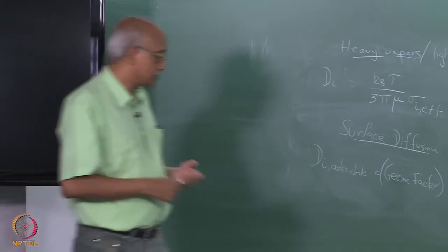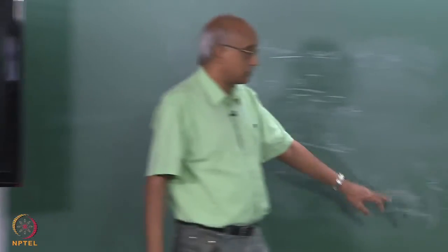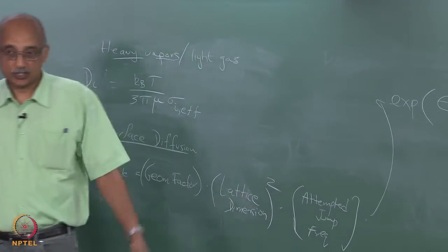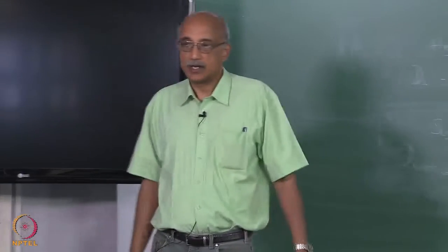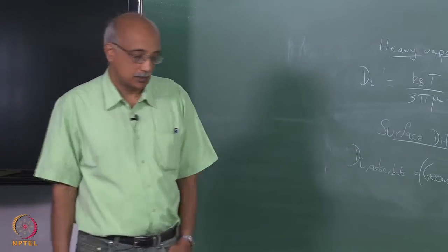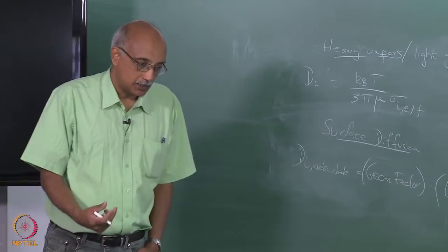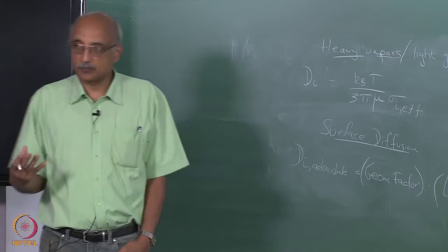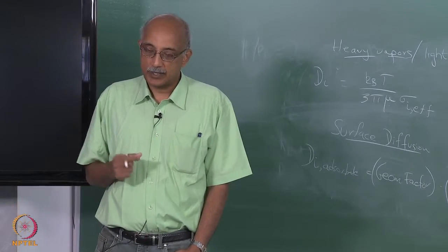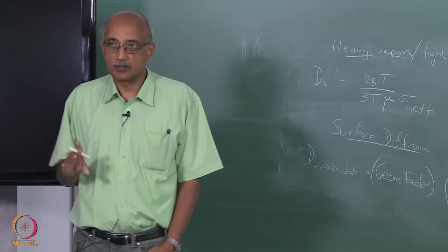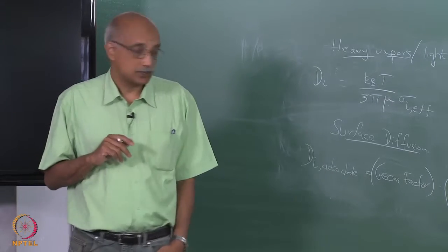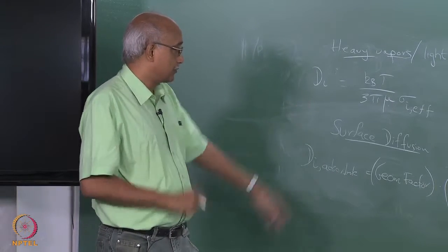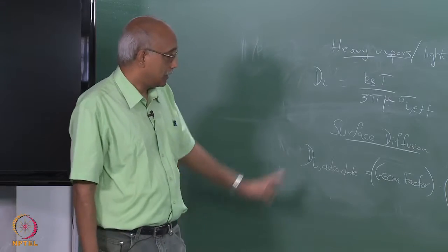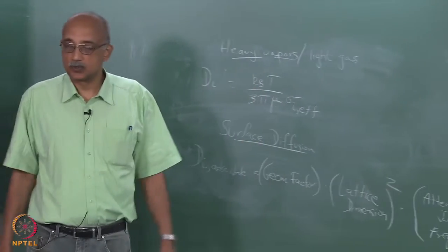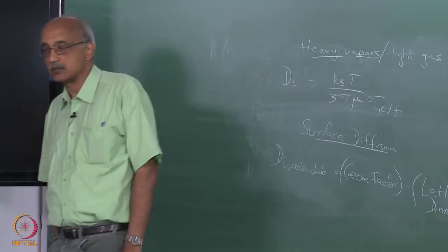For example, surface diffusion is dominated by temperature effects, but pressure has very little influence. Whereas, diffusion in the gas phase, as we saw, there is a very strong effect of pressure, inverse effect, whereas the temperature effect is more moderate, between T to the power 1.5 to 1.8. And in the case of heavy vapors, again, the temperature effect is quite significant, but pressure is not.